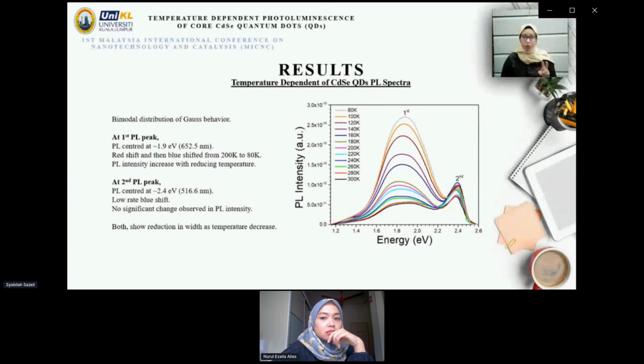We can see there are two peaks in the figure, first peak and second peak. This spectrum shows a Gaussian distribution behavior, displaying homogeneous broadening, due to the well distribution of cadmium selenide quantum dots diameter, approximately around 4.5 nanometer within the sample. The first PL peak is centered at 1.9 electron volt, while the second peak is centered at 2.4 electron volt.